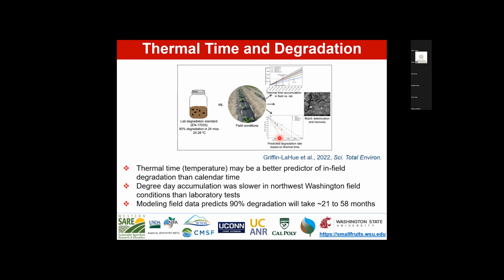And these temperatures might not be achieved in soil environments depending on where you are at, such as northwestern Washington, where we have cool soils. So what this study found is that degree day accumulation was slower in northwestern Washington, which is a measure of thermal time accumulation relative to the conditions in these laboratory tests, such as EN 17033. And so what the modeling data found here is that 90% degradation will take longer than that 24 months period because of our soil conditions and accumulation of thermal temperature, 21 to 58 months. And this would contrast to areas where you have warmer soils.